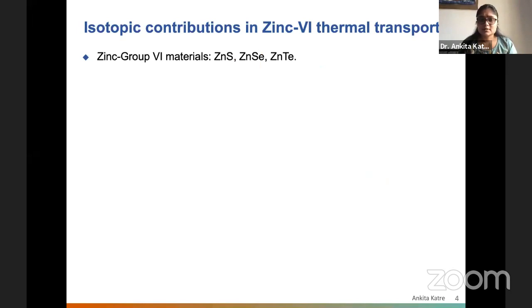So with this, I studied the isotopic contribution in zinc chalcogenides and tried to understand how much these isotopes could affect the thermal conductivity in zinc chalcogenides. There are several other studies, like gallium nitride, which have shown a very huge effect of phonon isotope scattering in the materials, needed to make a good prediction and to be in sync with the experiments.